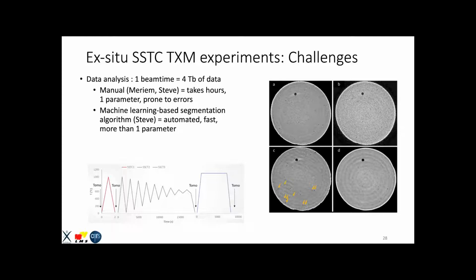So instead, Steve has been working on a machine learning-based segmentation algorithm, which is an automated technique, fast, with more than one parameter. So you can look at the size of the precipitates, you can segment them accordingly. By segment, I mean identification, so figuring out where they are. And it's not human, which is a good thing and a bad thing in the sense that you avoid the errors, but you also probably may miss a couple of precipitates just because, well, it's a computer and not a human.